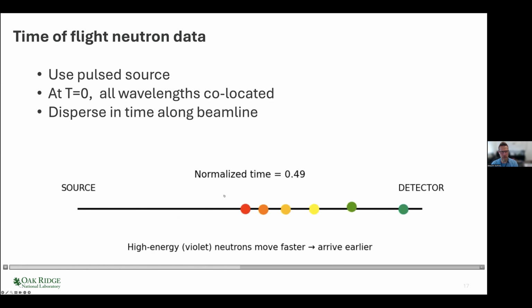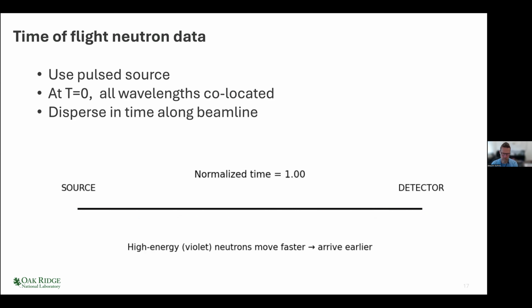So that looks a little bit like this, which I hope comes across in the transmission through Zoom, with the higher energy neutrons accelerating beyond the lower energy ones. And then essentially the only thing you have to do is measure when the neutrons were made, measure when they were detected, and from that measurement you extract their wavelength.